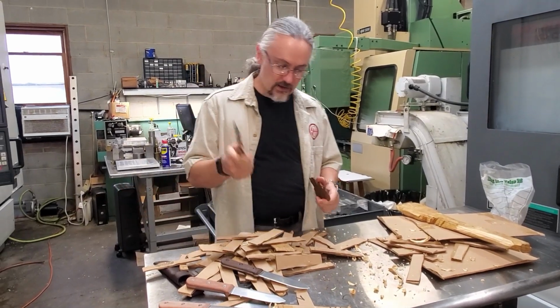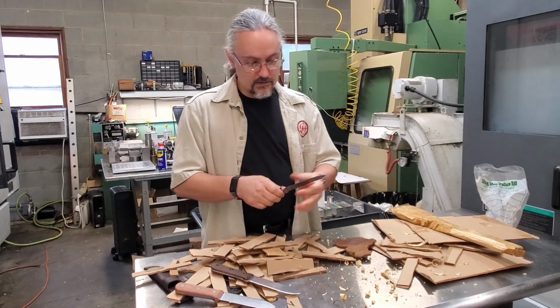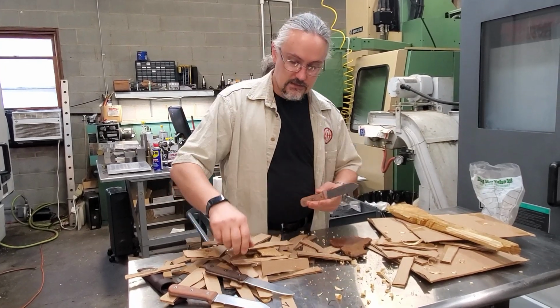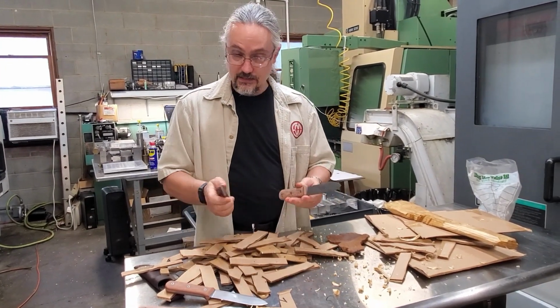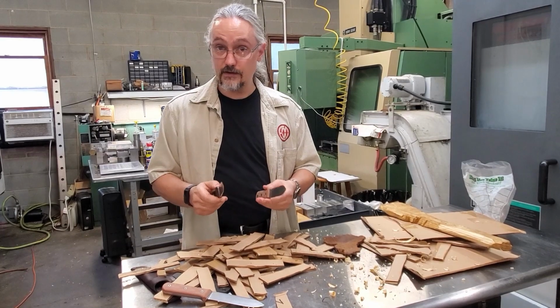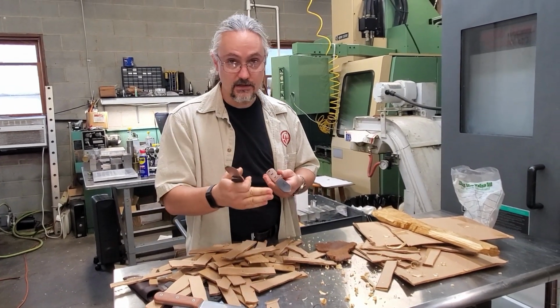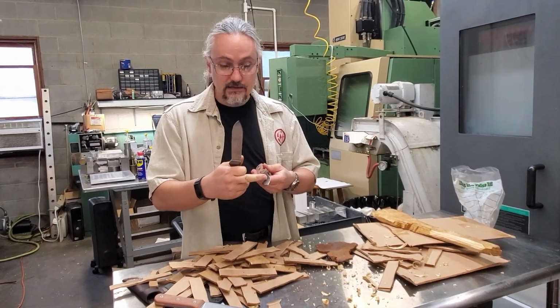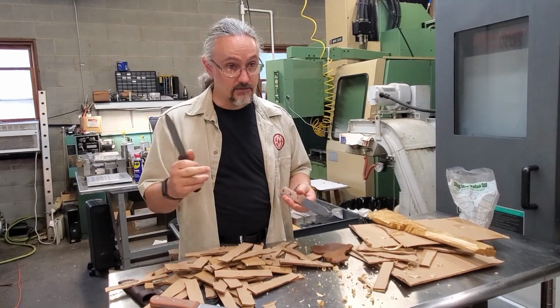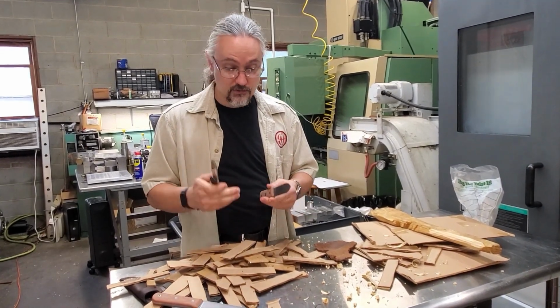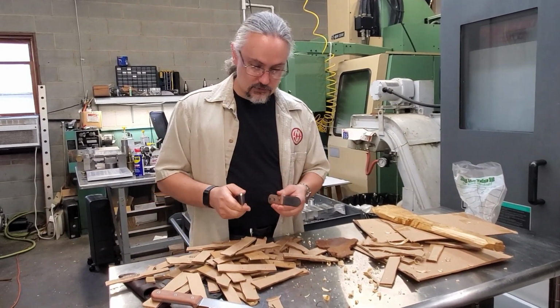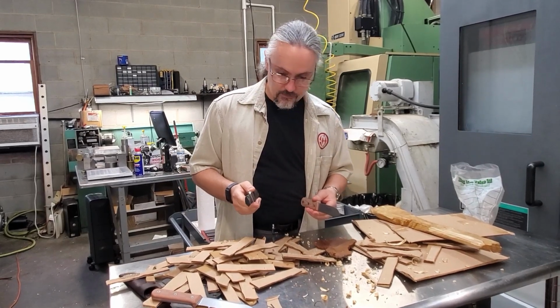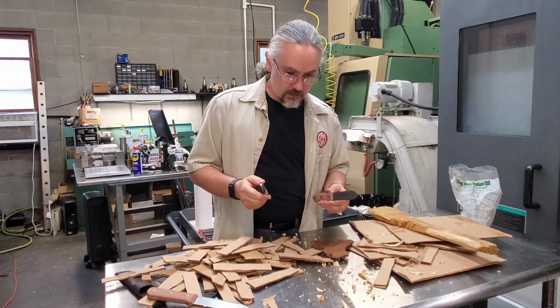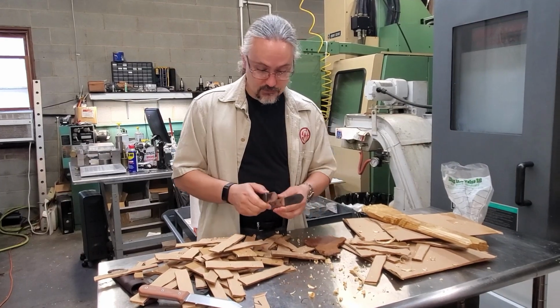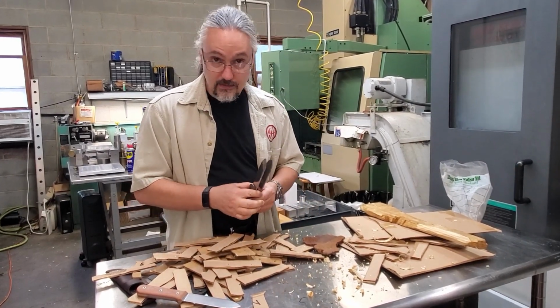So there's all kinds of things that you will find that you don't know matters, and until you're doing side-by-side testing like this and controlling your variables, like you need to have exactly the same edge angle, because 18 degrees is way different than 20, is way different than 22 when you're looking for these small effects. You got to control that precisely. So when you're optimizing a heat treat, there are a lot of variables, and there's variables that you're not going to expect to see that matter.